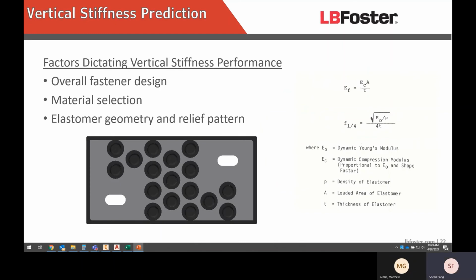So one of the initial steps in developing a DF fastener is to predict the vertical stiffness in order to hit the target specification. The main factors that go into a vertical stiffness calculation of a fastener is obviously the overall fastener design, how much of the rubber is being compressed, and also the different types of rubber that we use. We have different durometer rubbers in order to hit a target vertical stiffness, and also the elastomer geometry and relief pattern. The formula used on the right is what we typically will use to get a ballpark estimate of what our vertical stiffness is going to be when we start developing a fastener.